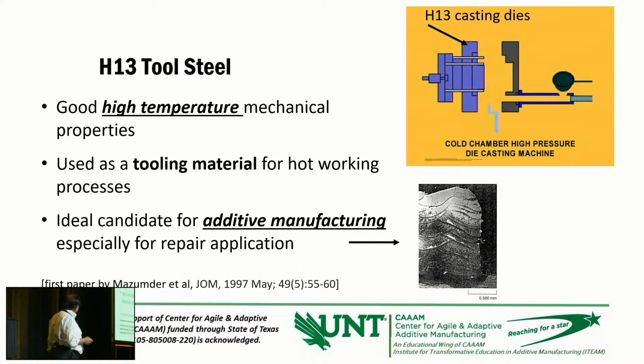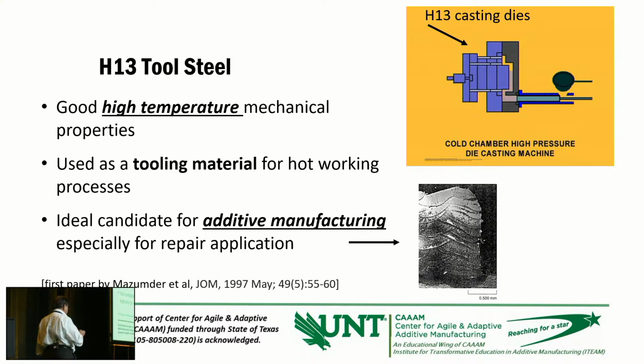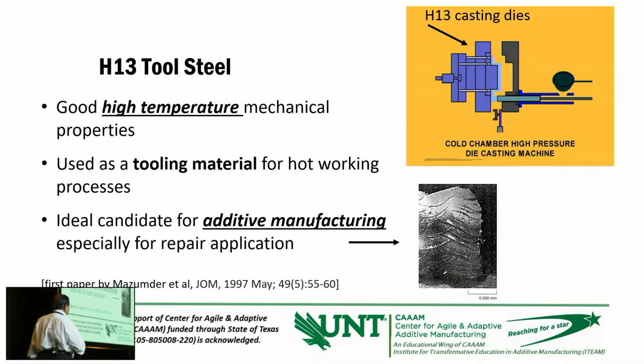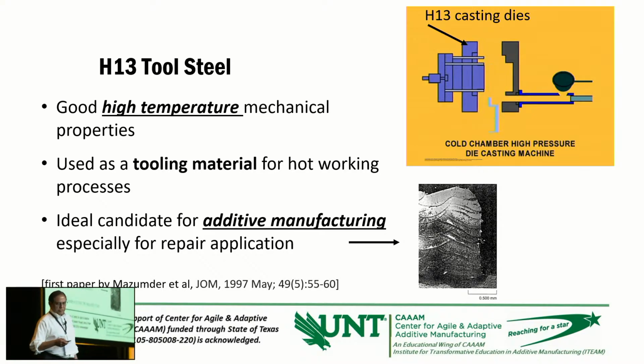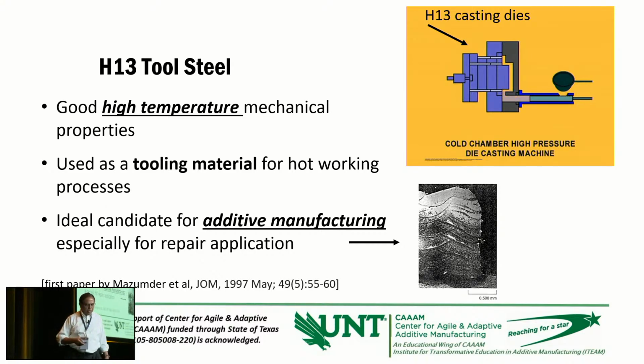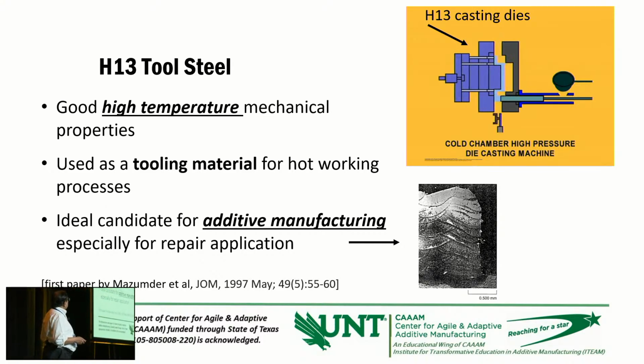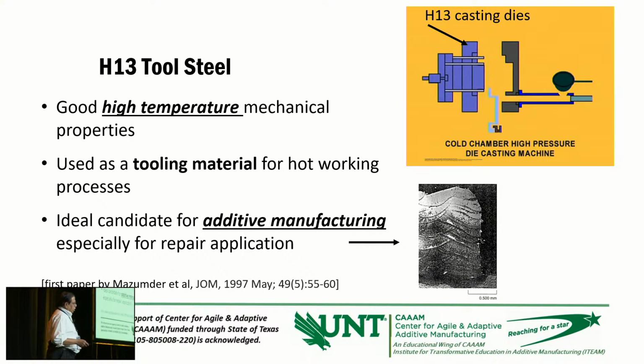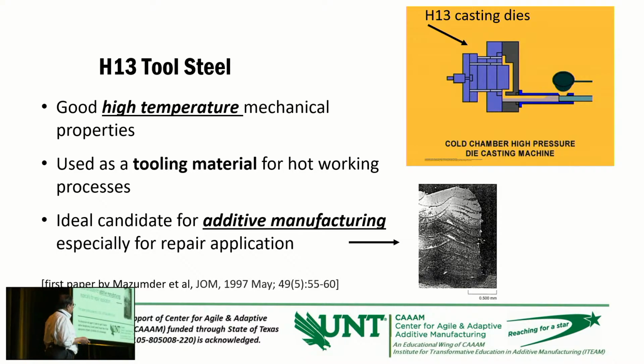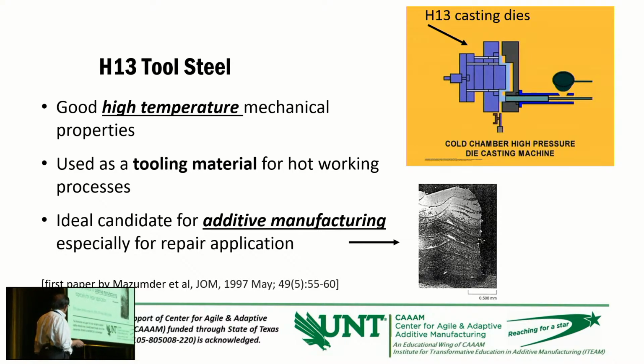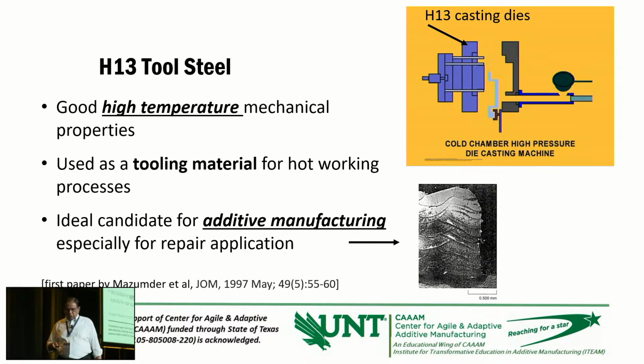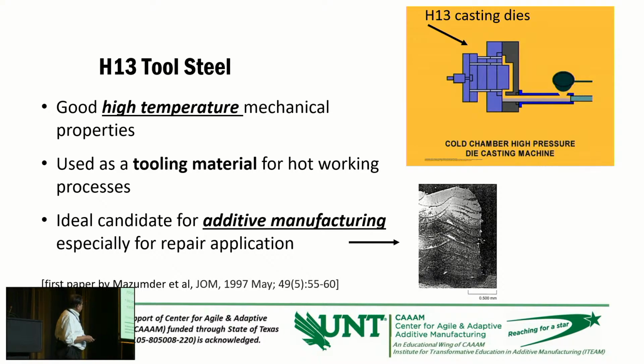But making the die out of this H13 is very expensive. So over the period of undergoing thermal cycles, this die starts cracking. They produce surface cracks, and then molten aluminum seeps into those cracks, and those cracks expand, and then they go out of use. And each die, depending upon the size, costs anywhere from tens of thousands of dollars to $500,000 to $1 million. So oftentimes the industry refurbishes those dies by grinding them, welding them together, and so on. So that's where these dies are very important, and the process of making this die takes months and months and months, and is very expensive and labor intensive.